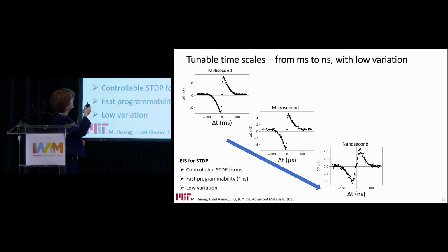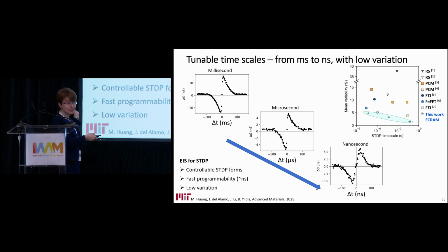So the biological process is on the order of tens of milliseconds, but of course you want to get computers with this as fast as possible, so it's tunable down to nanoseconds with these devices by voltage as well as electrolyte geometry. And very importantly, like in the DNN case, it's much more repeatable, controllable compared to other attempts of this STDP in the field, for example, with resistive switching, phase change, ferroelectric tunnel junction, or ferroelectric FET, which are all attempted in the field, and sometimes you look at the data and you can hardly see the form, and therefore the variability of those other attempts is much higher than what we can achieve with this ion intercalation electrochemical device. So it's deterministically controllable, to enable this STDP with different functional forms, tunable in terms of time response and much lower variation, which means more reliable.